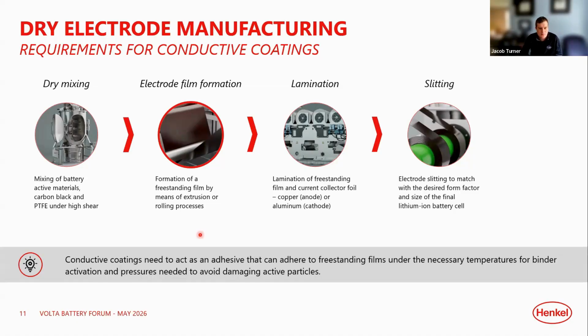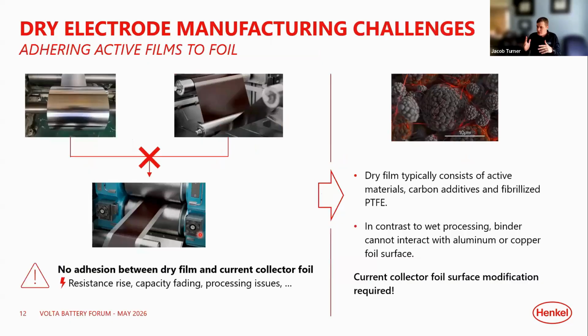So, when we start thinking of what properties we need from conductive coatings here, this is where we go from that traditional just coating standpoint to something that's now also acting as an adhesive that can adhere to these freestanding films under the necessary temperatures and pressures that are typically needed for different binder activations and to avoid damaging active particles. So why do we need this? As I said before, it's a technology enabler, and this slide summarizes that.